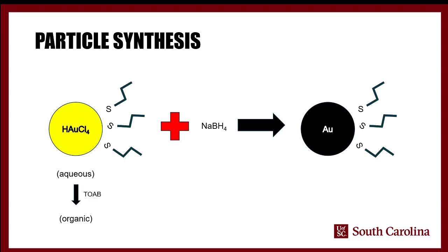And so this particular solution, once you remove the aqueous phase and wash the non-aqueous phase with water to make sure you've removed all the excess salt, the nanoparticle solution is actually very stable. It was stable on the order of months without any significant size changes or aggregation. And so that was kind of the important first step. So now I have a gold nanoparticle solution with a short carbon length ligand, and so now we can get